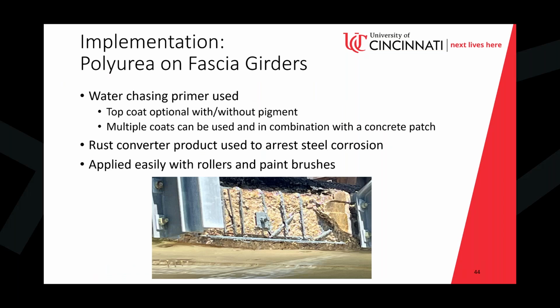So we applied this product. It's a water chasing primer. It actually really likes if the surface is initially wet. You just have to clean off the surface, remove excess concrete, just like use a pressure washer or air to clean the surface. No special surface prep required. You can apply a top coat with or without a pigment, and there are multiple coats that you can use. And you can also do it with a patch or without a patch.